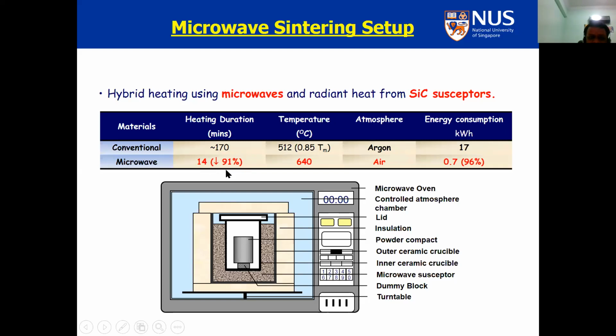Why is it important? Now you are able to sinter almost 10 parts rather than 1 part in the same time. Temperature 640. We can increase the rate of sintering. Remember the Arrhenius law, any reaction is an exponential function of temperature. We can even do the sintering in air and no need to use argon. How much energy we save, and you can translate that into the fuel consumption, is 90 to 96% in this situation. So basically it's a very good energy saver.